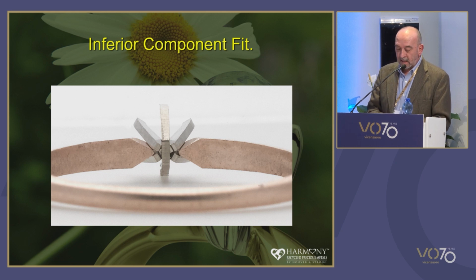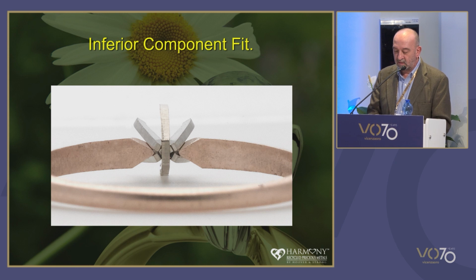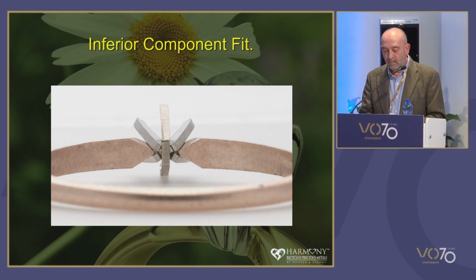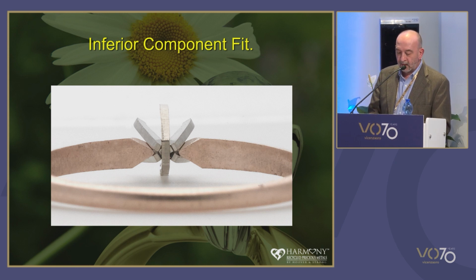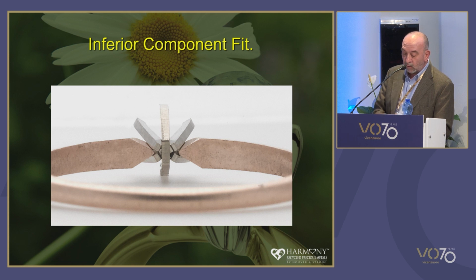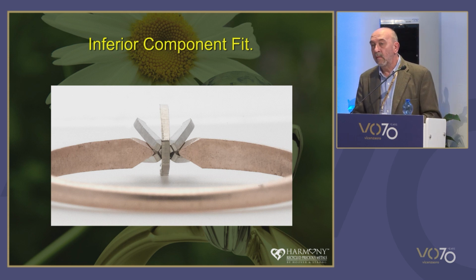After soldering through the belt furnace, the components were joined, but not to a satisfactory standard that could be finished without repair work. And the porosity identified was, as you see, voids generated by a function of poor component fit. So we removed the pre-finishing step and the joint quality improved and we were back to normal.